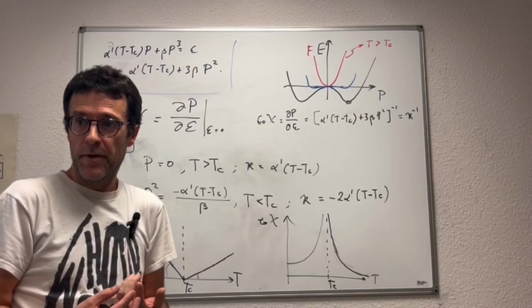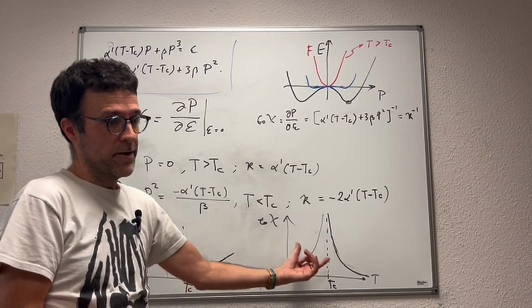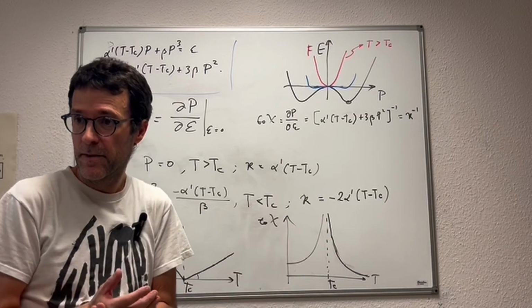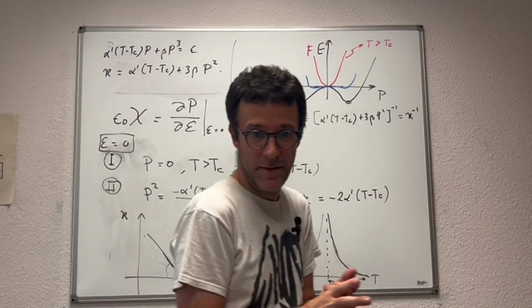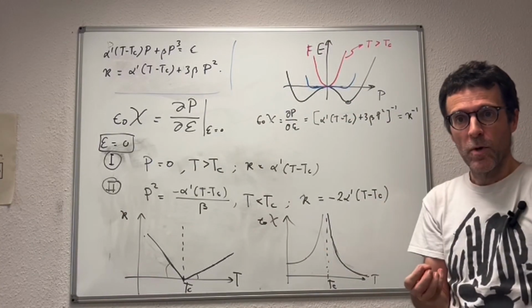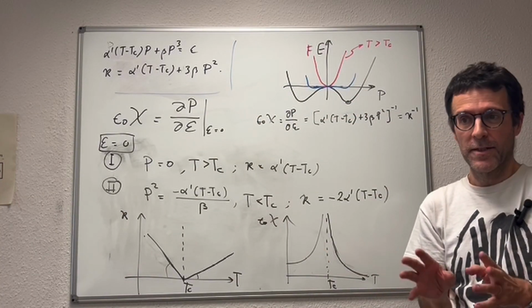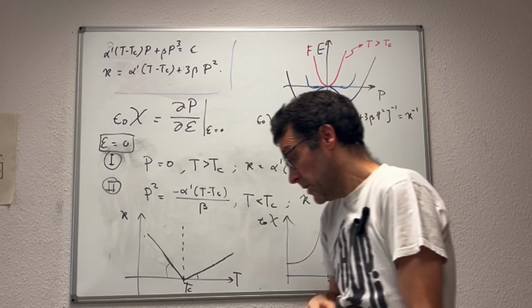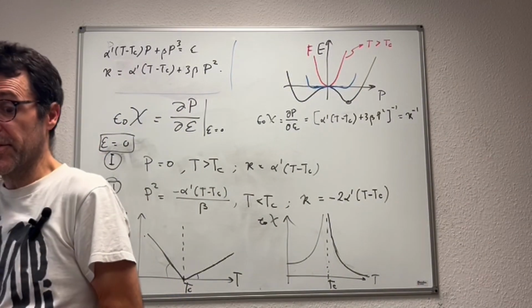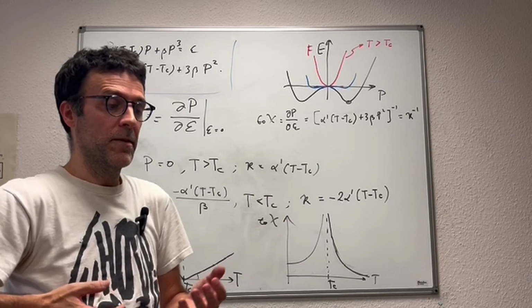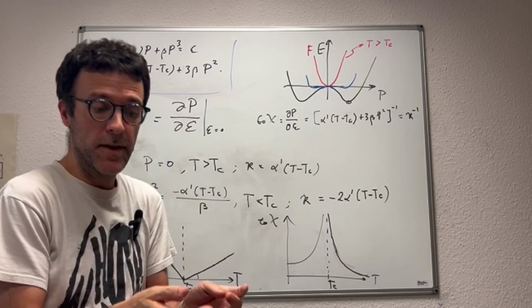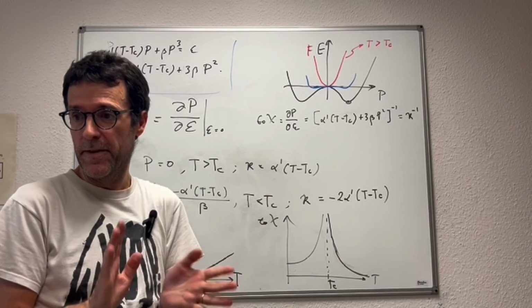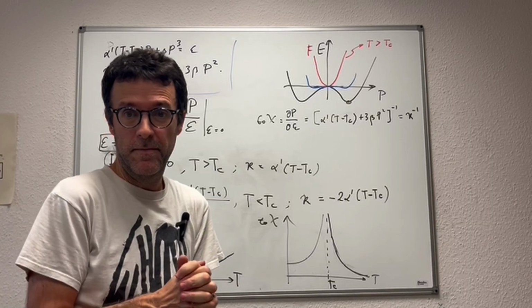Of course, you never measure infinity, but it's not uncommon in ferroelectrics to measure susceptibilities of 10,000, 40,000, where, just to give context, silicon has a susceptibility of about 10. Okay? So if you want to make a material that is reactive to electric fields, or whose behavior can be changed by applying an electric field, a ferroelectric is probably your kind of guy.